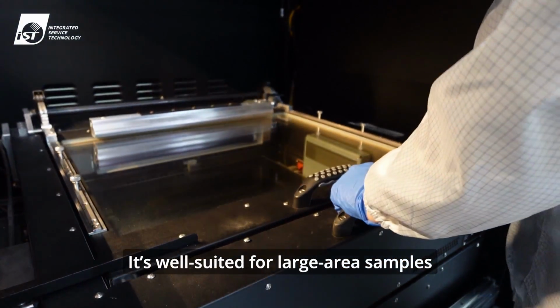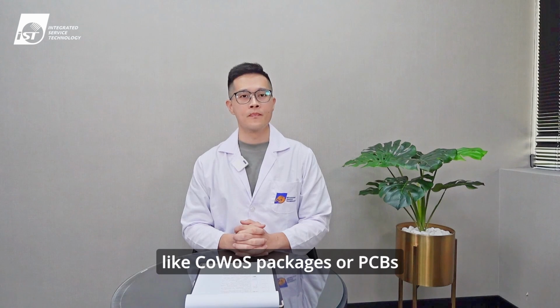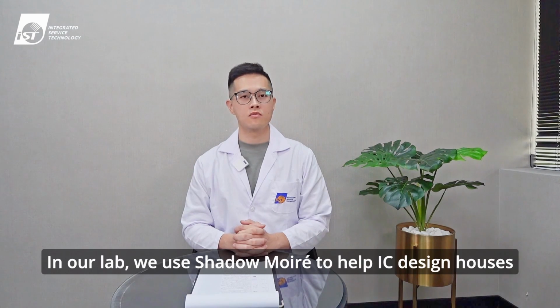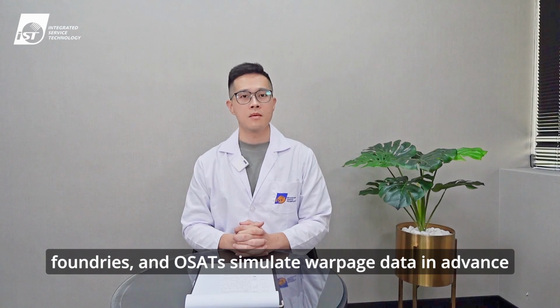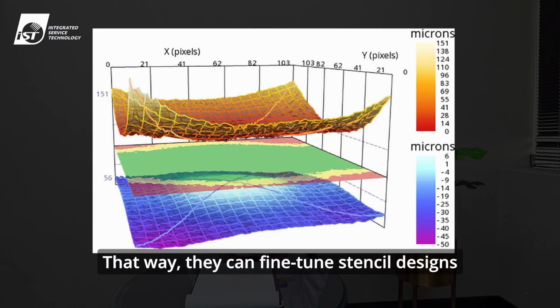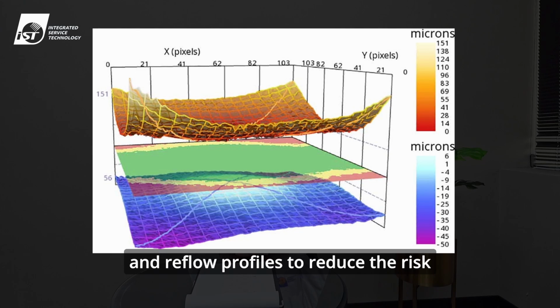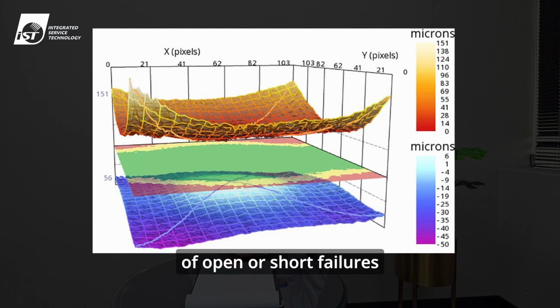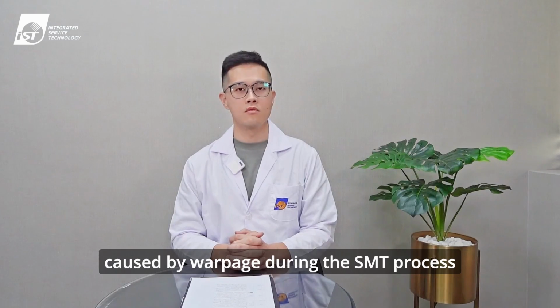It's well suited for large area samples like CoWoS packages or PCBs. In our lab, we use Shadow Moiré to help IC design houses, foundries, and OSATs simulate warpage data in advance. That way, they can fine-tune stencil designs and reflow profiles to reduce the risk of open or short failures caused by warpage during the SMT process.